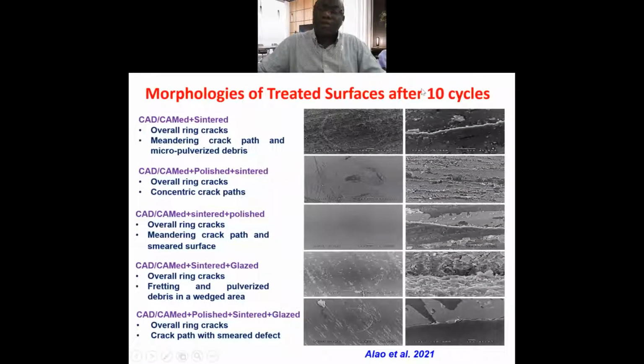So when the number of cycles was increased to 10 cycles, you can see for the CAD-CAM sintered the enlargement in the ring crack.